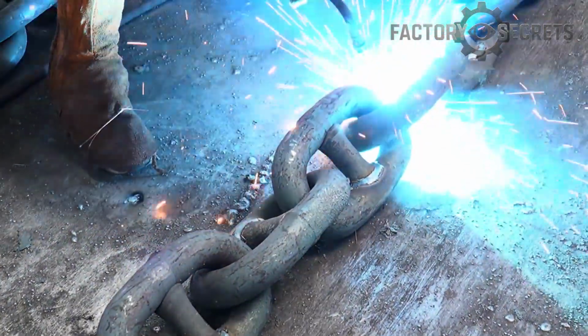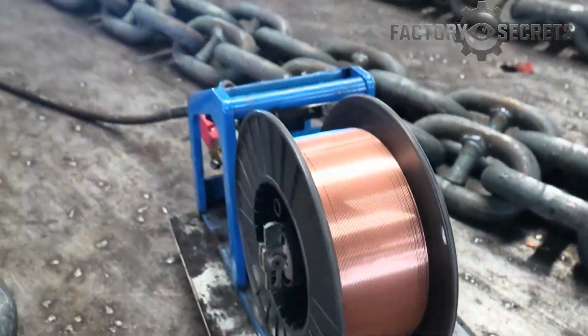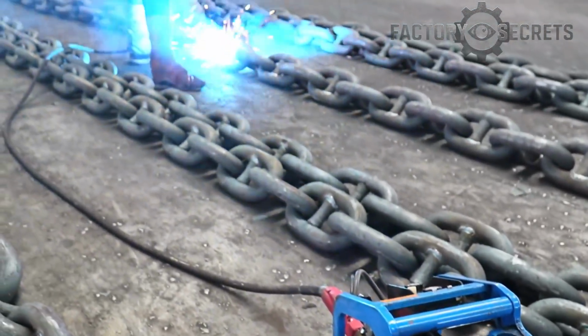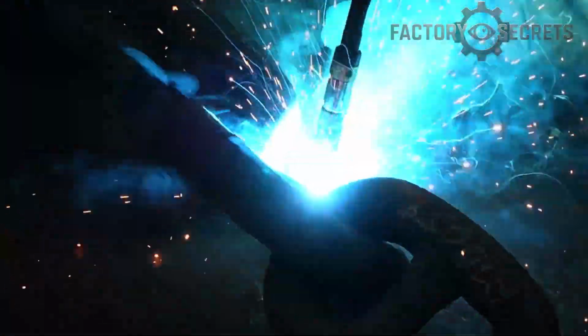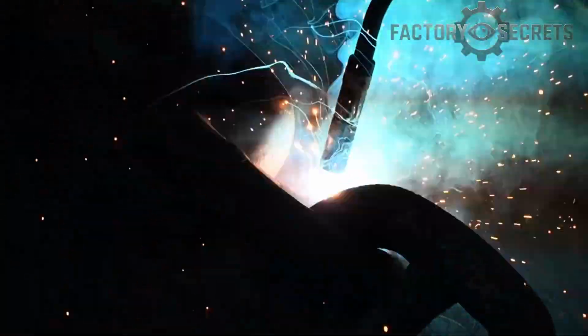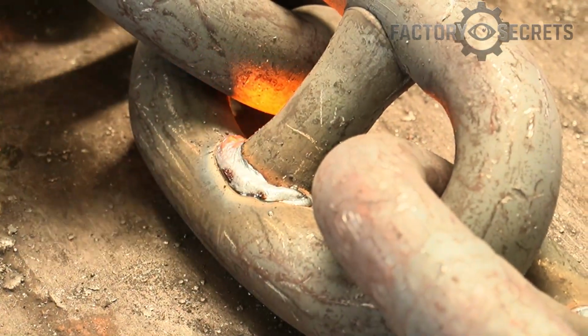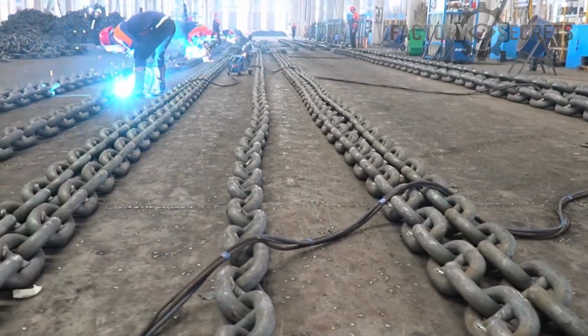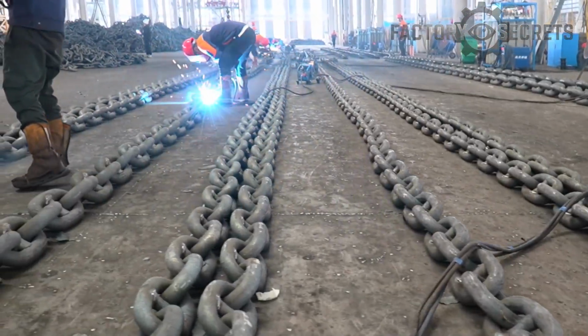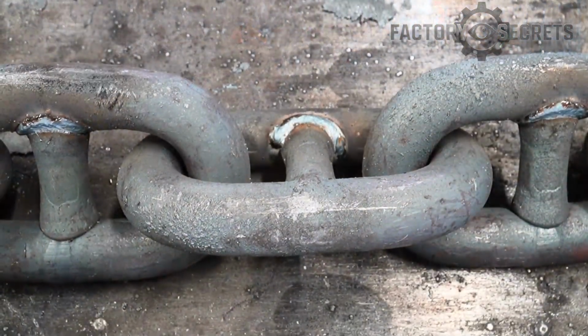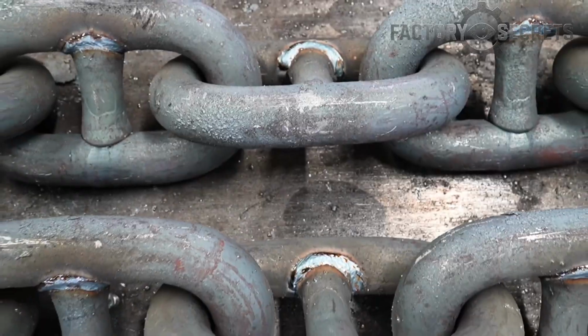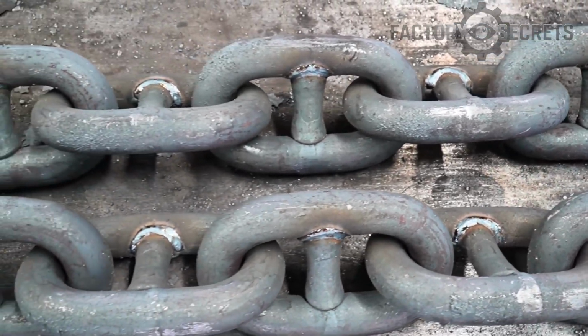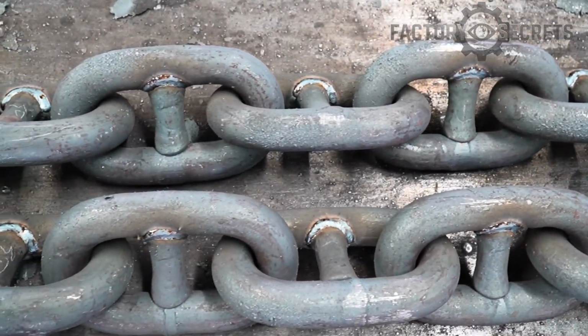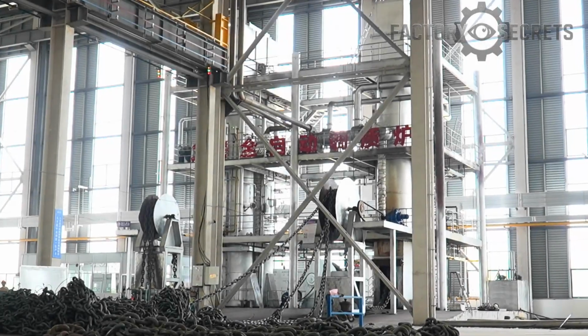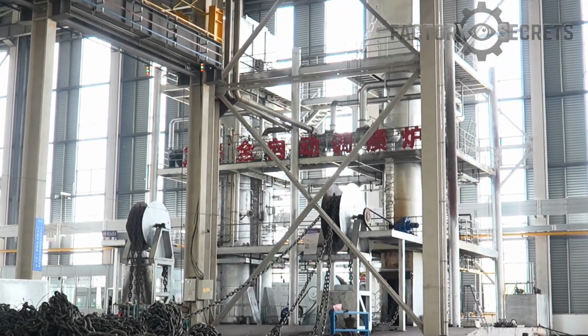Why manual? Because this weld requires precision that a machine in this configuration can't guarantee. The welder has to read the metal, control the heat, and ensure full penetration on each side of the stud. One welder per end. Consistency through craftsmanship. When this step is complete, the stud isn't just sitting inside the link. It's part of it.